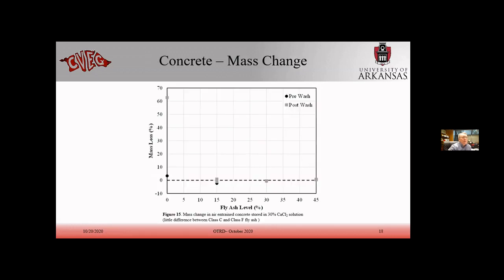And then mass change, we had a pre-wash and a post-wash. Well, the pre-wash, Casey just kind of gently got some of the stuff off the outsides of it and measured it. The post-wash, as you can see the gray one up here, wasn't a pressure washer, but he gently ran kind of a water hose over the concrete to remove the loose concrete. And you can see that the cement-only ones lost about 65% of their mass. When you added the 15, 30, 45% fly ash, you can see they didn't lose much mass at all, which is also evident in the pictures.